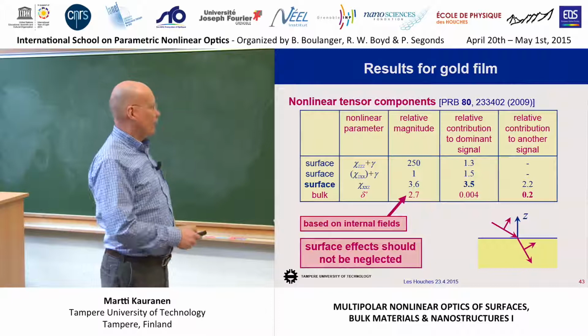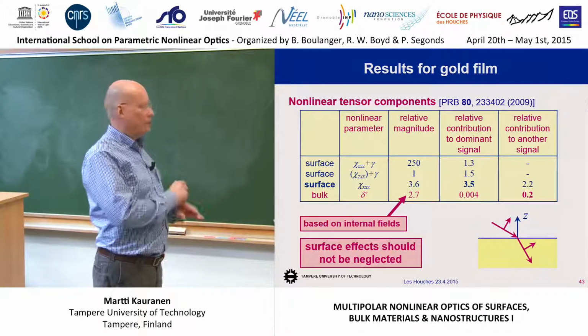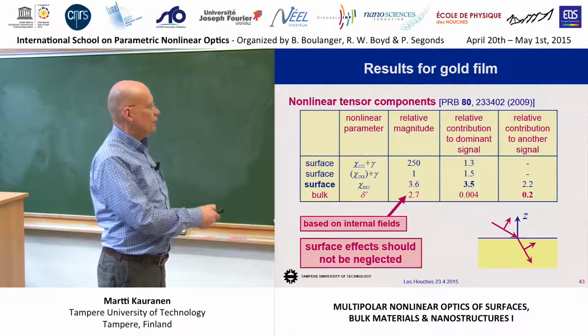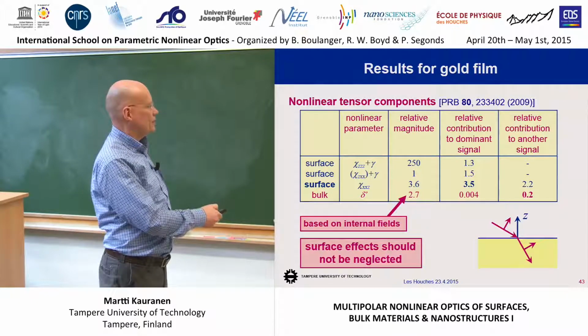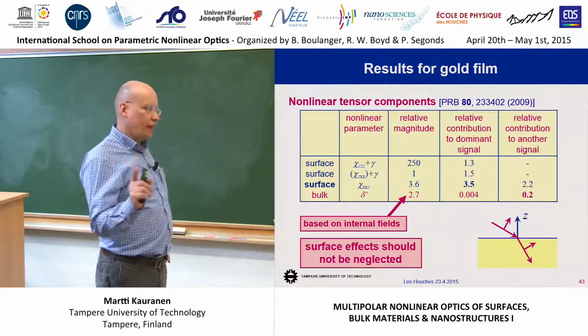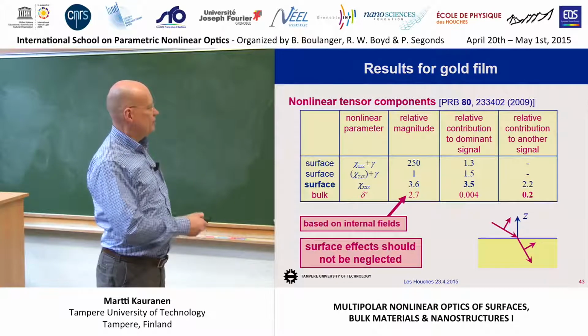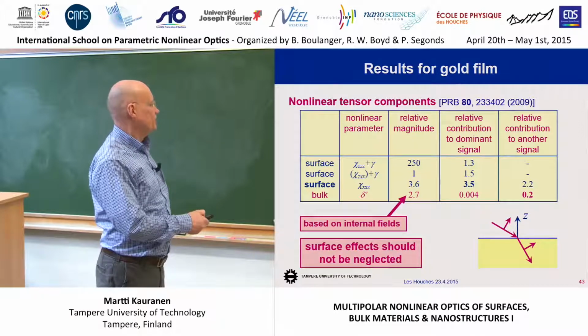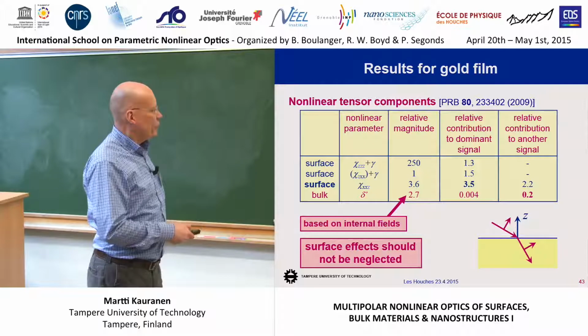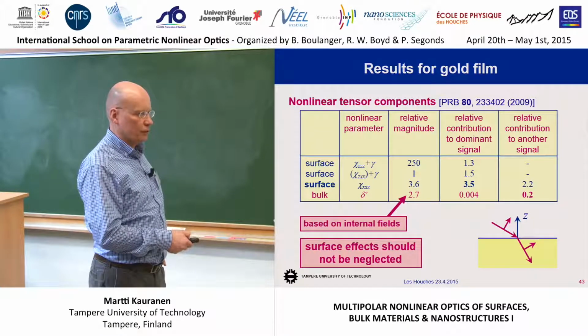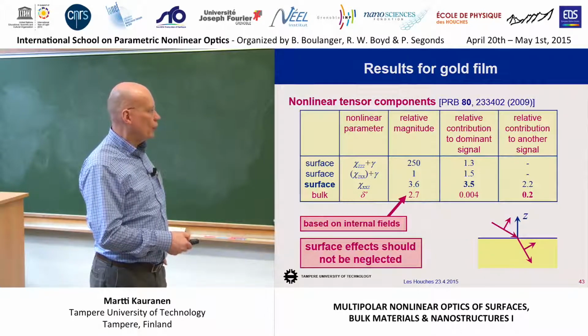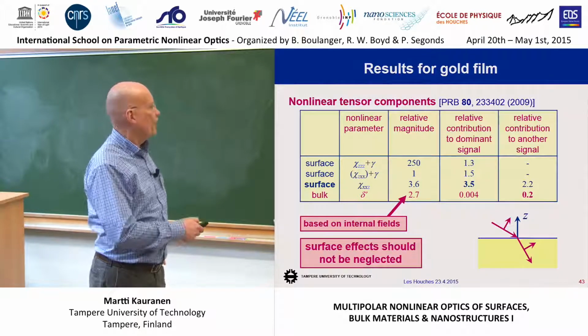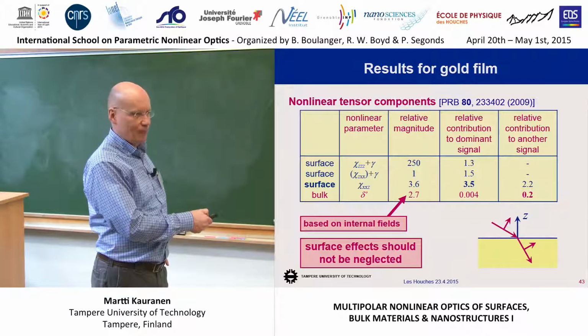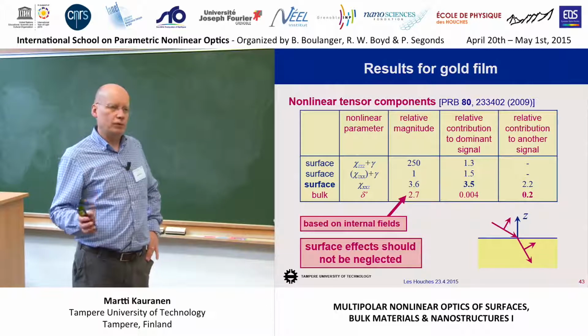And now you could say that, okay, ZZZ 250, it's basically 2 orders of magnitude higher than these 2 other parameters. So in practice, nothing else matters than this ZZZ surface response. But you have to be really careful, because if you used external fields, this would become much, much weaker. The trouble is, it's not trouble, but it's just a fact, that ZZZ, because when you go across the interface, it's the normal component of the field which is discontinuous, right? And in the case of metals, the Z component of the field is basically screened by the metal, and therefore, in order to account that the Z component inside the metal is very weak, you have to account for that sort of artifact by making the respective tensor component really strong. And then, in the end, what matters is that how do these tensor components contribute to the measured signals, right?